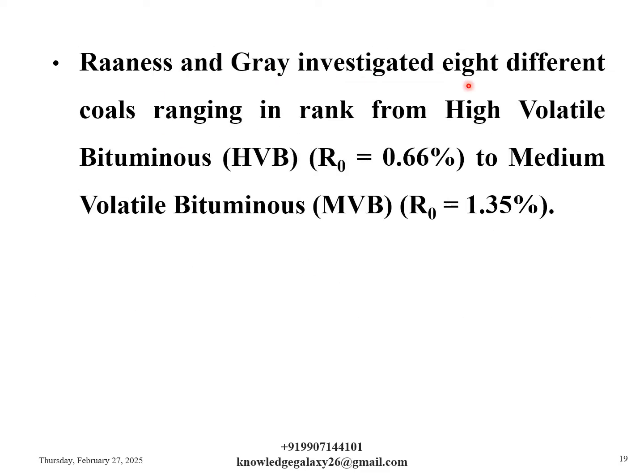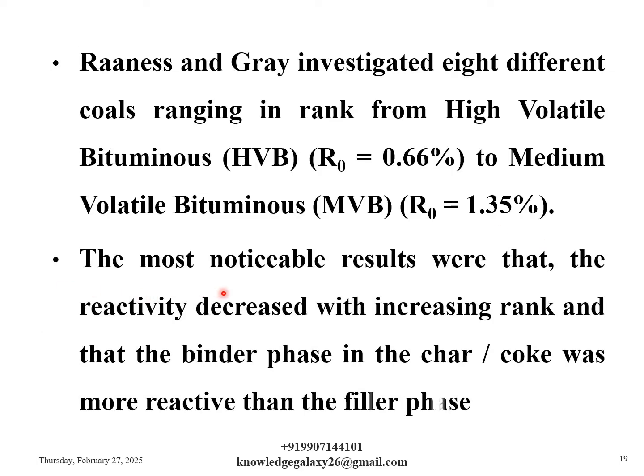Raanes and Gray investigated 8 different coals ranging in rank from high volatile bituminous, that is HVB, Ro equal to 0.66%, to medium volatile bituminous, that is MVB, Ro equal to 1.35%. The most noticeable results were that the reactivity decreased with increasing rank and that the binder phase in the char or coke was more reactive than the filler phase.